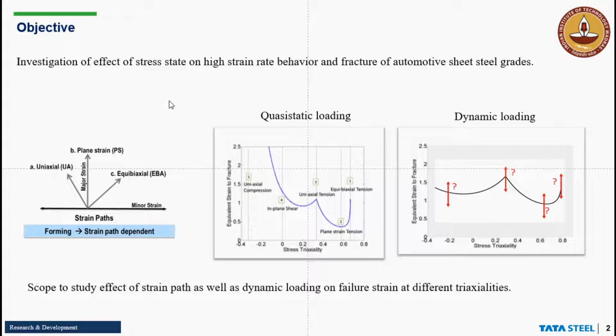The current fracture modeling actually takes quasi-static loading into account. There could be different stress states at which experiments could be done. But in reality, we should be having dynamic loading, the equivalent strain to fracture. It should be mapped based on high strain rate loading with changing stress triaxiality. So there is a scope to study the effect of strain path as well as dynamic loading on failure strain